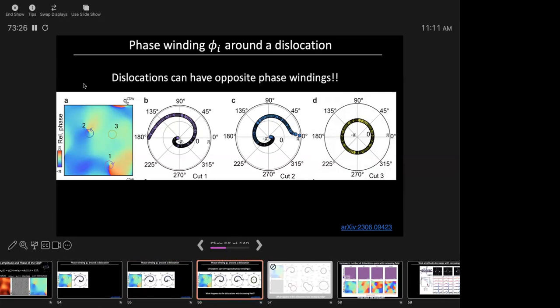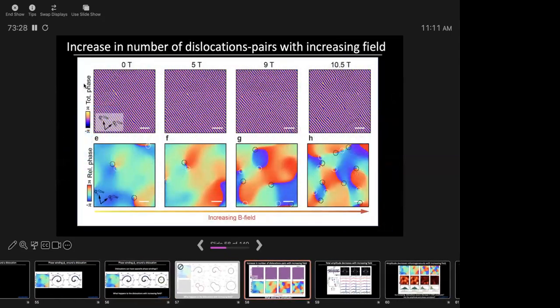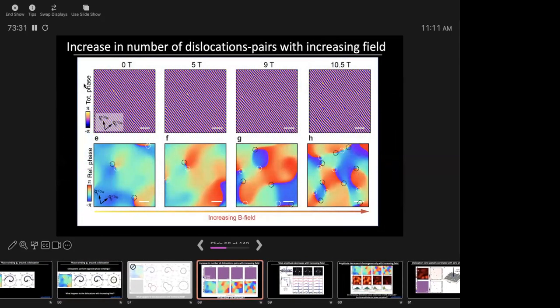Okay. And now let's ask what happens as you increase field. So this is 0 Tesla, 5 Tesla, 9 Tesla, 10.5 Tesla for the sample where the CDW disappears with magnetic field. What we find is that you have an increase in the number of dislocations. And not only that, the dislocations come in pairs. So the color here represents the winding that I just showed you. So you can see pairs of dislocations with opposite winding emerge as you increase magnetic field. Okay. So this is really cool.